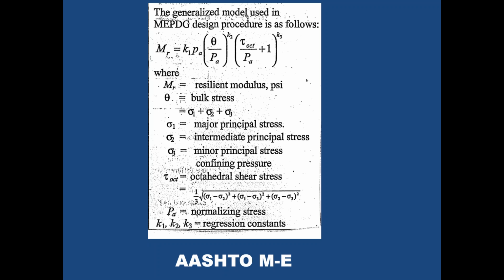But you'll find, for example, in the analysis of the LTPP test data from the various sites all over the state, there was not a very consistent effect of K3. In fact, in some cases, it went the wrong way. And so this model is, I would suggest, one that is very sensitive. You need to know from your test data exactly what those values are.